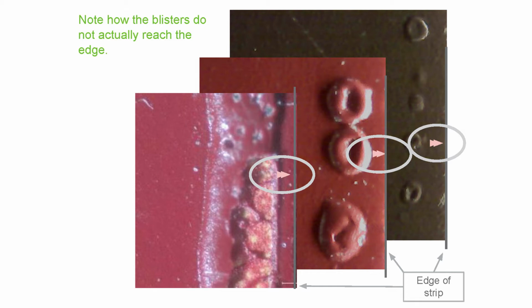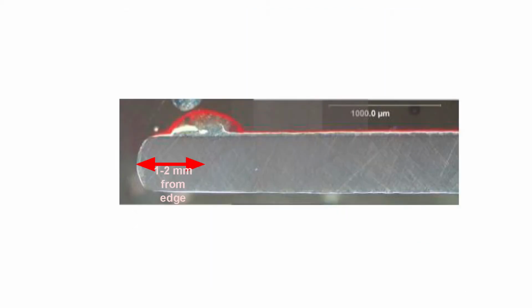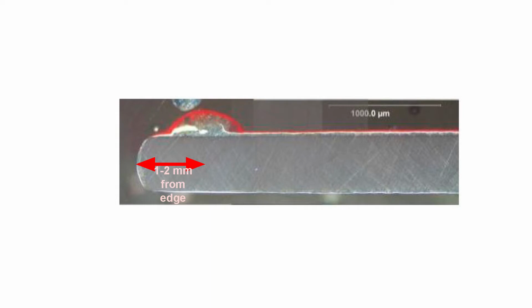Over here, the same thing. You have an area that's not got blisters, and then blisters. There's always this tiny little gap. And a cross-section of that would look something like this, where first of all, you see that a piece of metal, of course, does not have a perfectly flat edge, so that may be one of the explanations. But typically, about 1 to 2 millimeters from the edge is where you have the height of that blister or that bead. So that bead can be about 1.5 or 2 times as thick as the paint in the center of the strip. So instead of 15 or 18, maybe it's 25 microns or 30 microns. Now that's a challenge to try to prevent solvent popping on something that thick.